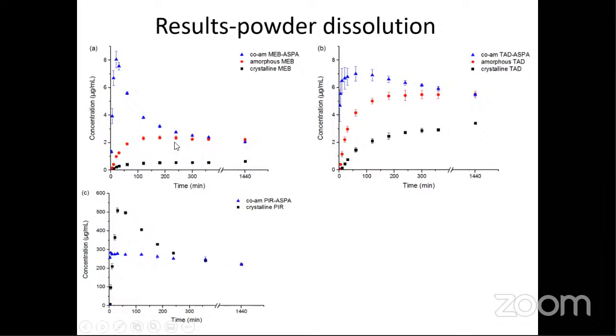The final concentration after 24 hours is almost the same as the amorphous one. So basically, from this case, we can see mebendazole co-amorphous showed very nice supersaturation curves. This is very good for improving the bioavailability of these drugs after oral administration. In the case of tadalafil, a similar phenomenon was also observed.